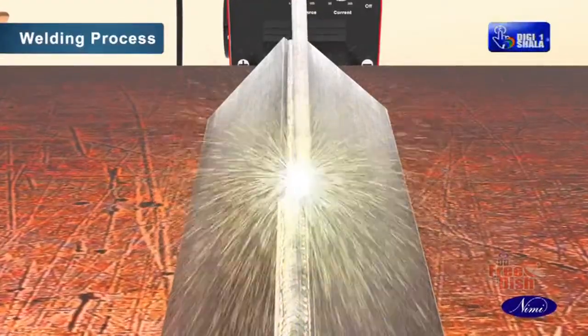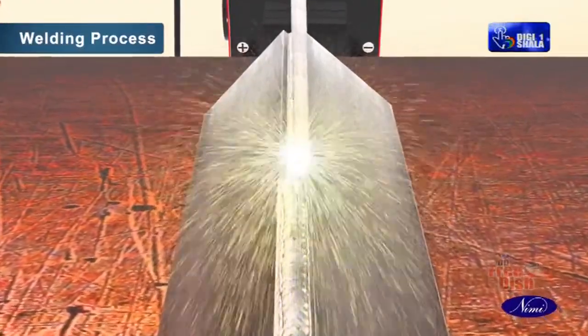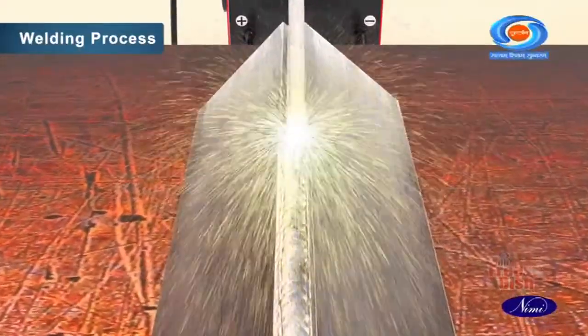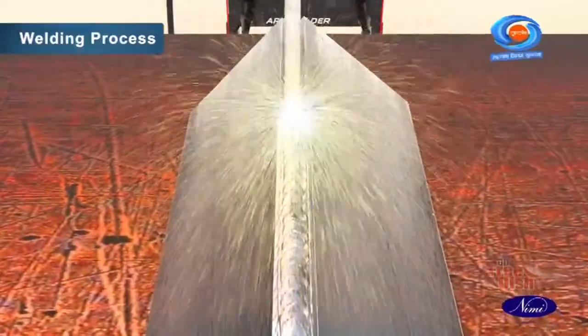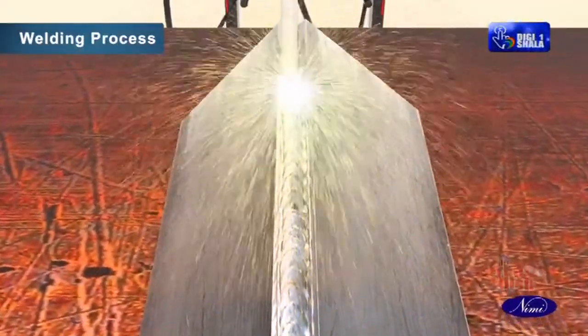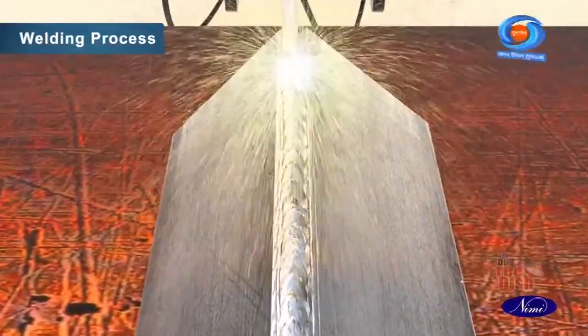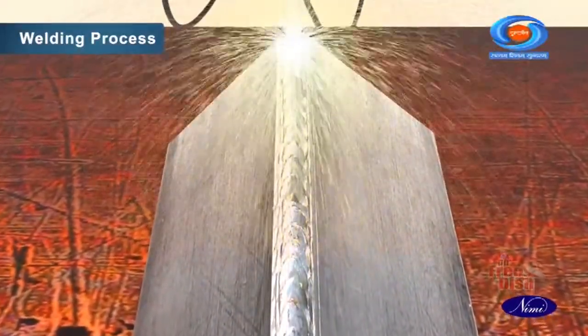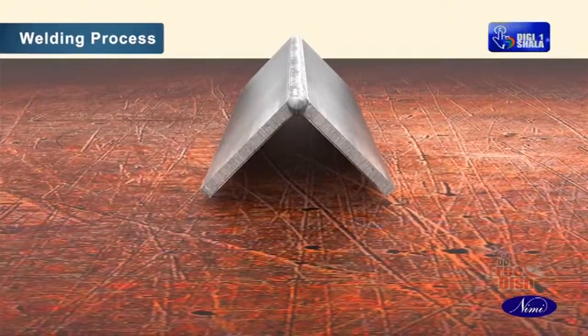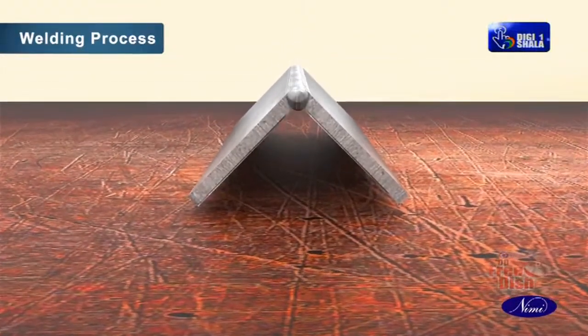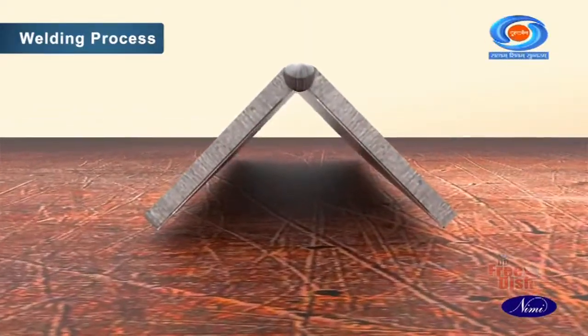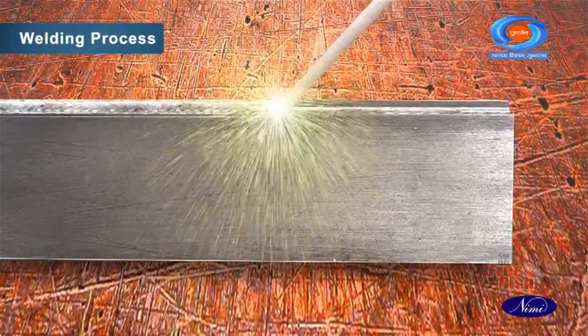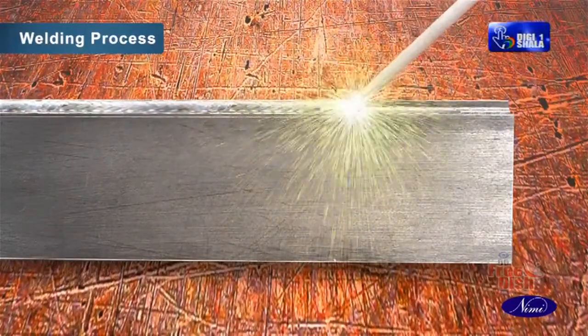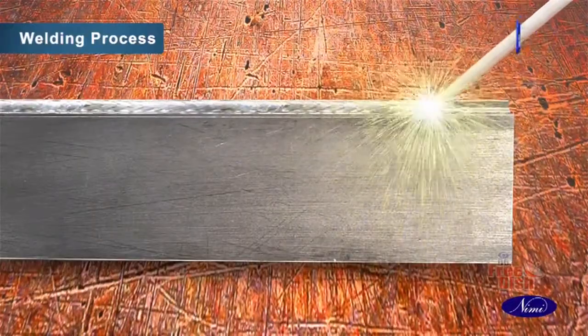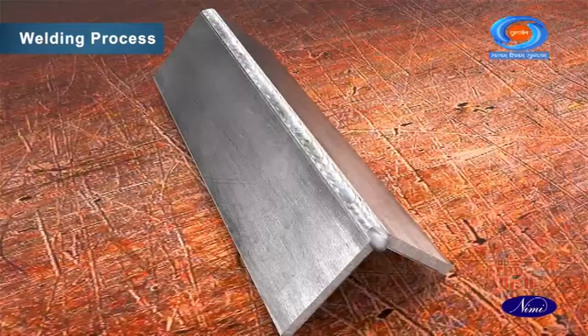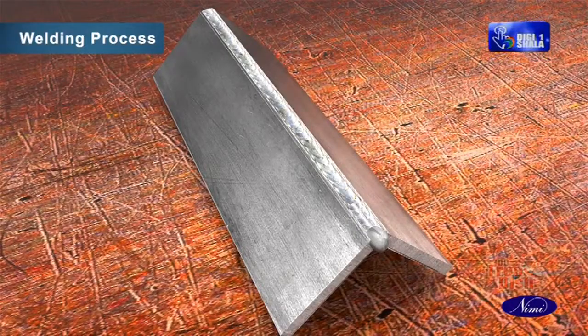Each movement of the weave from one side to the other will deposit more metal, and that takes more time. Ensure restarting and stopping of the beads correctly. The usual defect on the final layer of weld is edge plate melted off. This can be eliminated if care is taken to weave the electrode to the required extent so that the edges are just fused. The arc should not be focused on the edges at all.